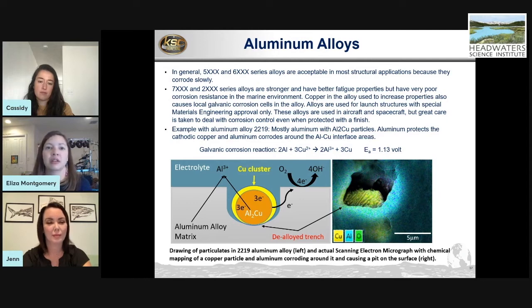But the reason why they are corroding is the same thing we kind of learned before, where there is a dissimilar metal here. The copper, aluminum copper, think about it just like a galvanic cell. It is a piece of copper next to aluminum. They have 2 different potentials that are high enough apart. You can see they're 1.13 volts apart. That's pretty high. And if it has a coating over top of it, you're good to go. It will protect both of those things from the environment.